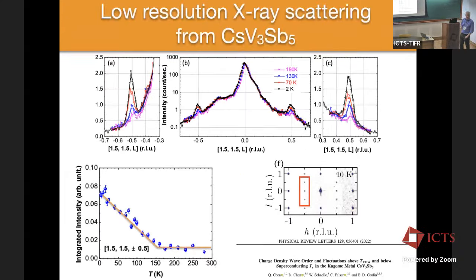Okay, and so the net result of all that is that you can see things in low resolution scattering that you cannot see in high resolution scattering because they're too diffuse for the high resolution scattering. There's a mismatch between the resolution function and the phenomenon. Okay, so this is our low resolution X-ray scattering data from these samples of cesium, vanadium, and antimonide.